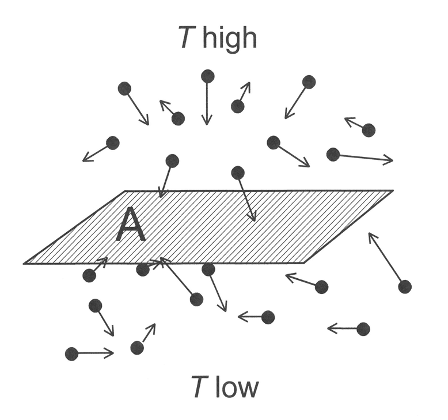with K₀ a constant. For pure metals such as copper, silver, etc., L is large, so the thermal conductivity is high. At higher temperatures, the mean free path is limited by the phonons, so the thermal conductivity tends to decrease with temperature. In alloys, the density of the impurities is very high, so L and, consequently K, are small. Therefore, alloys, such as stainless steel, can be used for thermal insulation.